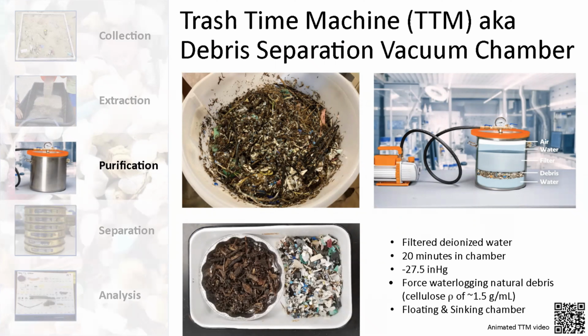The porosity of natural material is much larger and more abundant than that in the synthetic material. So as we pull the air out of that material, and once we release the pressure back into it, the material acts like a sponge and is going to pull all of that water into its pores and cells, force waterlogging that material in a matter of moments. This process is taking 20 minutes, and we are pulling down to 27.5 inches of mercury.